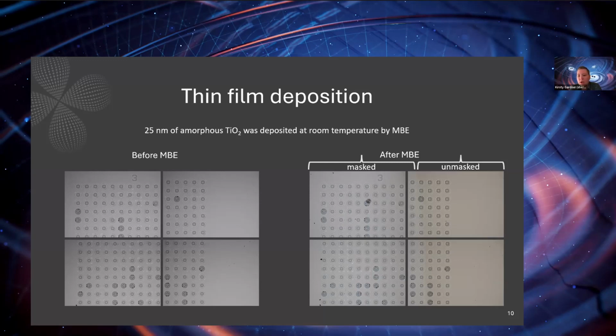So we covered the sample with aluminum foil to protect or to keep half of it covered while it was in the MBE. And you can see from the optical microscope image that that worked quite nicely. We have not quite half the sample, but half the sample is covered in titanium dioxide and half of it is left clean. Now, during the fabrication of these microdiscs, we made the choice to change the disc radius across the chip. So no 2 microdiscs are identical, which complicates a little bit the calculation of mechanical losses we'll see later, but otherwise this worked well.